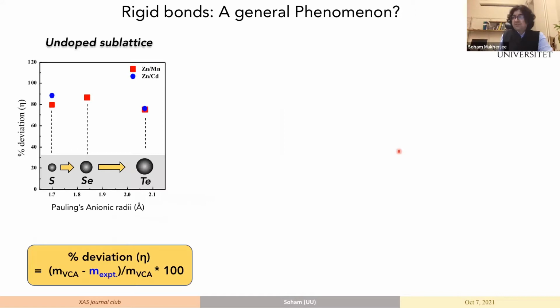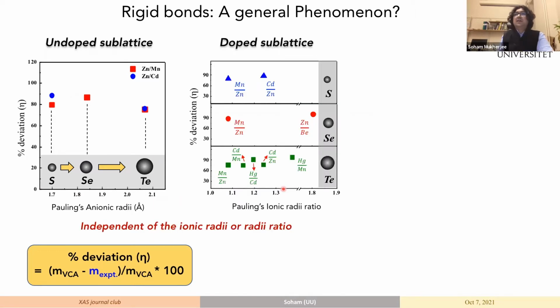And what we saw is that this is a very general phenomenon, and a lot of work has been done with this. We looked at a very specific doped sublattice, and then we changed the ionic radii. Nothing has changed. The percentage deviation, which is the difference between the virtual crystal line and the experimental line slopes, is very, very small. So zero would be perfectly the virtual crystal line. And there are a ton of other systems which show very similar behavior. It looks like it's very independent of the ionic radii or radii ratio.